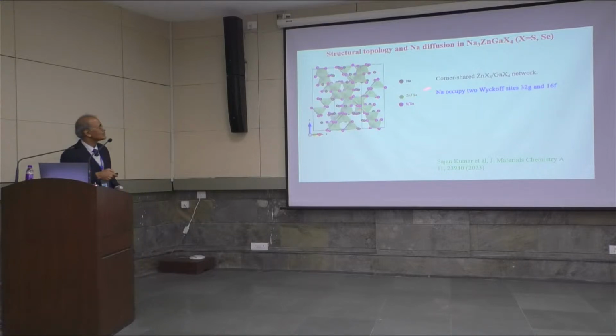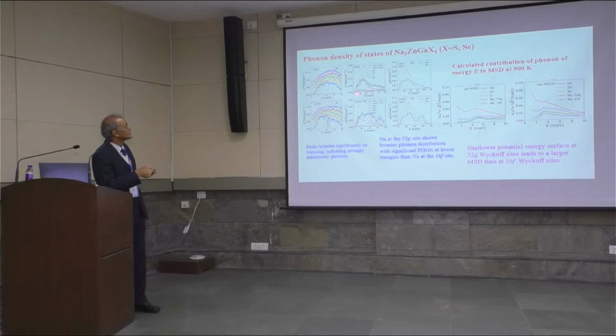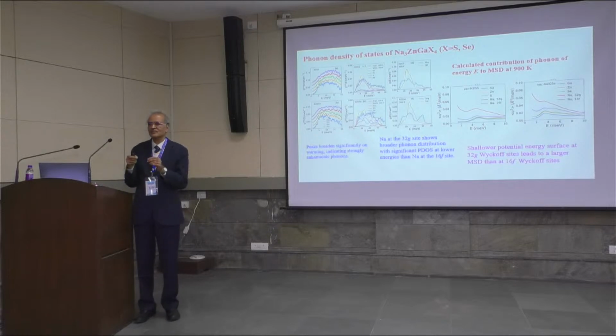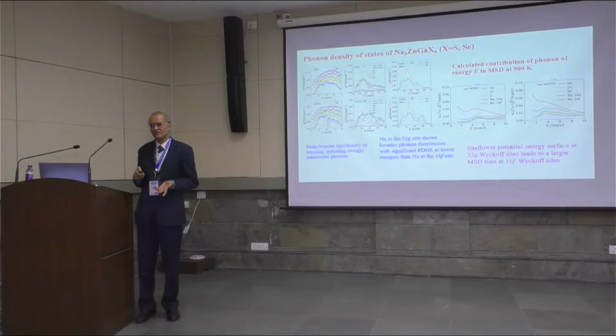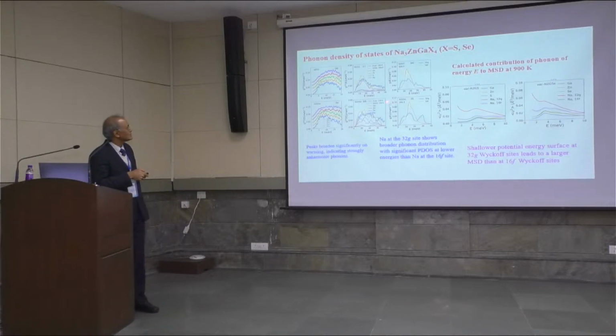Okay, and we are trying to see what kind of features can identify the diffusion process. So first, these are the phonon density of states measurements as a function of temperature. And what we essentially see here is that the phonon peaks broaden with the increase of temperature. And the broadening is like, if you have harmonic phonons, the anharmonic interactions lead to broadening of the phonon structure. Then further, through calculations you can identify the different components of the phonon density of states. This would be called the partial phonon density of states, which are atom specific. So for the different atoms in the material, you can see what their contributions are to the phonon dispersion curves.